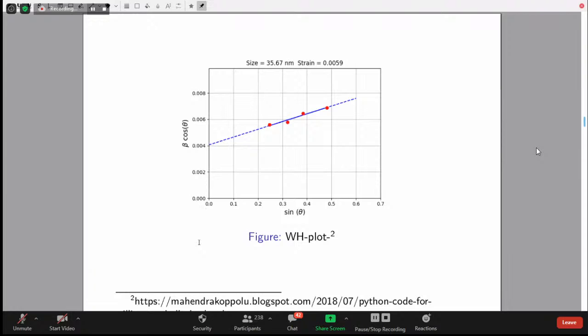Okay, Professor. Yeah, and here also we have several issues like alpha 1, alpha 2. Students never bother about there being an alpha 2. If they see a broad peak, they will fit it with one single Gaussian and say that it is that broad, but they have to see there is an alpha 2 contribution in the X-ray diffraction. First we have to strip out the alpha 2, then we will have the real widths, then we should proceed. So these are the cares we need to take. Some of the diffractometers still have beta also, which means on the left hand side you also have a certain amount of broadening, but we will know that only when we have a diffractometer at hand. But majority in India, we just send a sample out and get the data. So those are the practical difficulties we have.